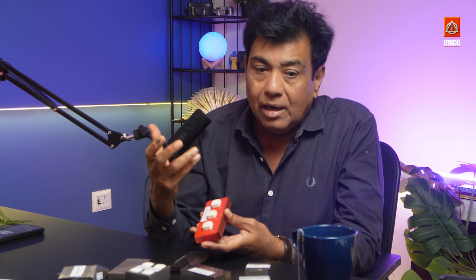These are basically polyurethane materials, very light, and we are able to embed the ceramics inside. Now this has a different application altogether. So these are used in wet condition where the temperature is below 60 degrees, and it is the slurry and all these kind of things which get mixed while conveying the material. So these are very effective, very light, and work excellent at low temperature. The ceramic is the one that takes care of the wear items.